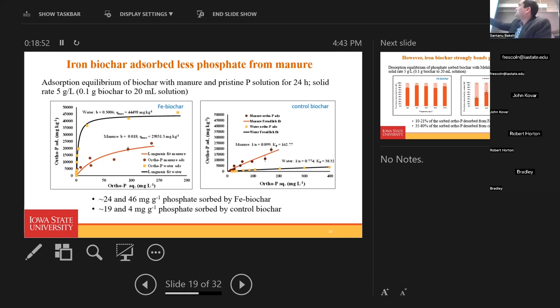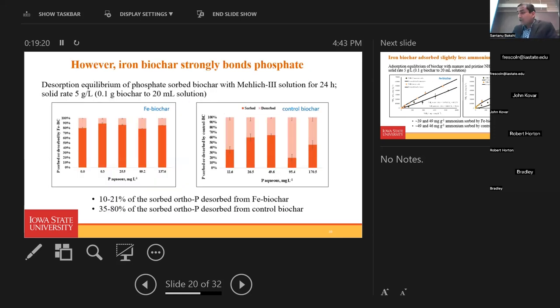So the phosphate is actually absorbing on that specific site. On the other hand, the control biochar is more complex, non-specific physisorption. So that's why it is following the Freundlich isotherm. I gave some numbers, 24 and 46 milligram per gram of phosphate for iron biochar. But for the control biochar, only 19 and 4 milligram per gram of phosphate was absorbed. However, iron biochar strongly bonds phosphate.